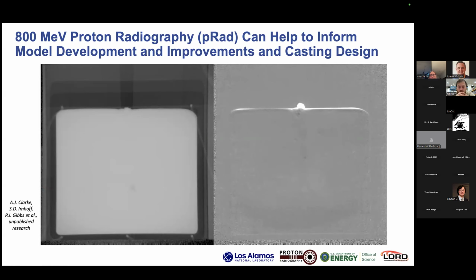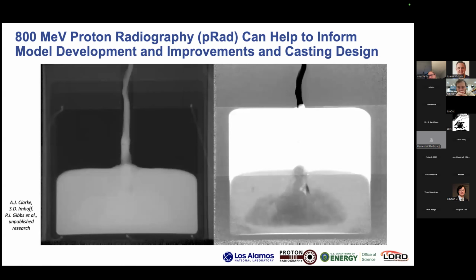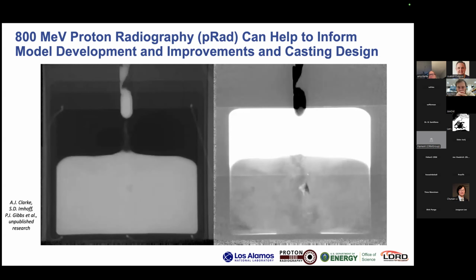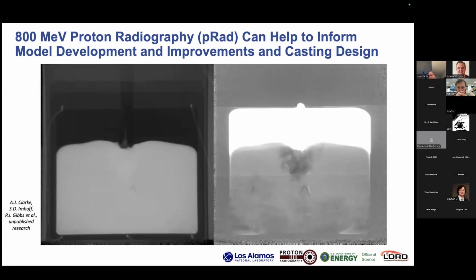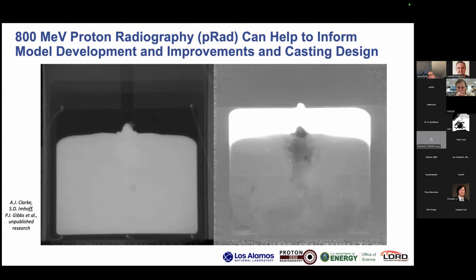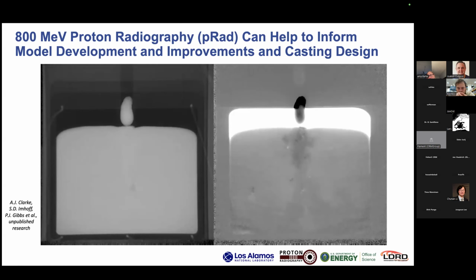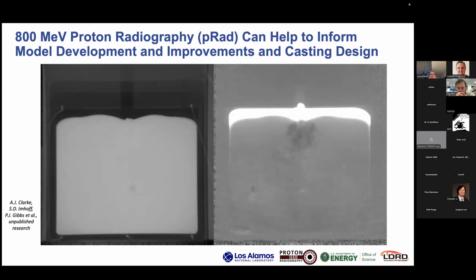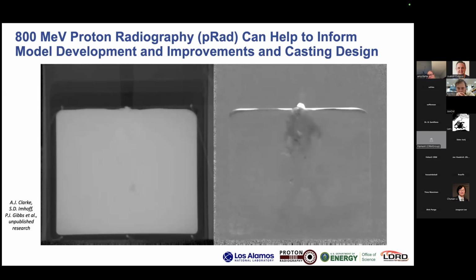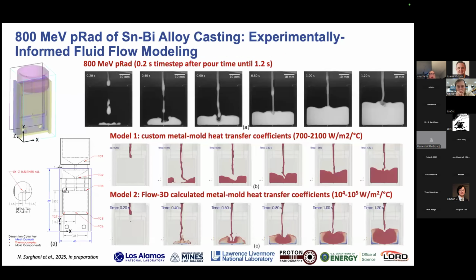So in this example, I'm going to show you an alloy melt, eutectic tin bismuth. That's halfway up the crucible, and then we're going to be dropping in molten bismuth liquid. So you can see the actual fluid flow patterns that develop in the melt. So it's pretty cool that we can see that, and seeing that type of flow behavior can be important for things like computational fluid dynamics and really understanding and doing casting design. And so that's some of the work that we've also done in the past.